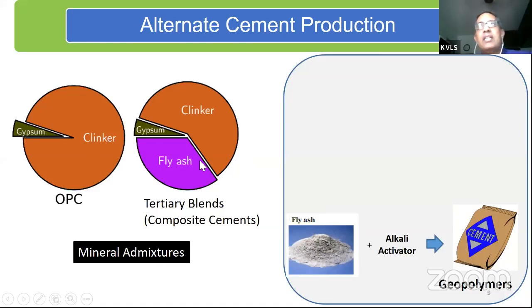Now we are already starting to look at replacement strategies for cement. The idea is to produce cement which uses less clinker. It is the production of clinker that uses limestone. It is the production of clinker that is associated with the carbon footprint and with the energy requirement. So one of the things to do would be to look at replacement of clinker in the cement, and we are looking at the replacement of clinker with waste materials like fly ash and slag, both of which are basically post-industrial waste materials.